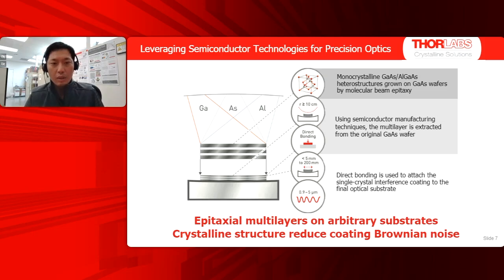So then how do we make these crystalline supermirrors? I've talked a lot about them. They are just a different way of making a very high reflectivity coating. We start with gallium arsenide and aluminum gallium arsenide multi-layers that are grown by MBE. It's a semiconductor technology. We grow them on a native substrate, and then we lithographically define a die that we can separate, just the multi-layer, from the original growth substrate, and then we directly bond it onto arbitrary optical substrates. So, for instance, glass.